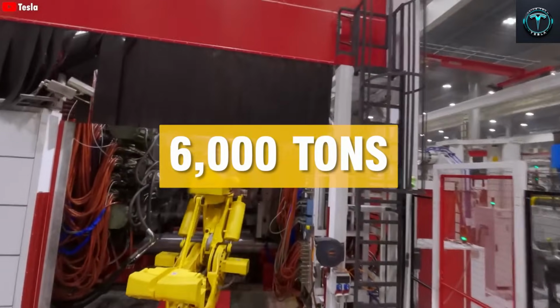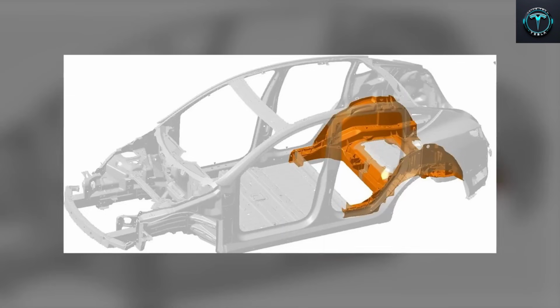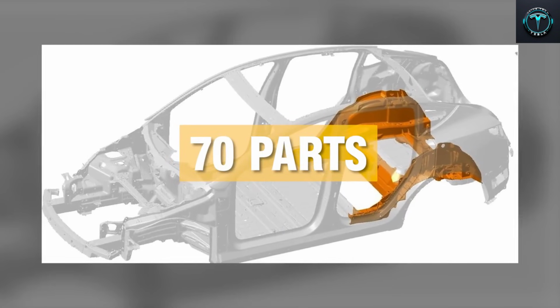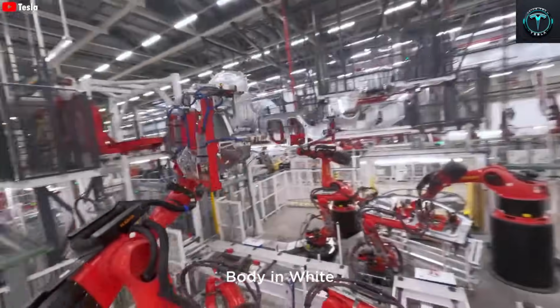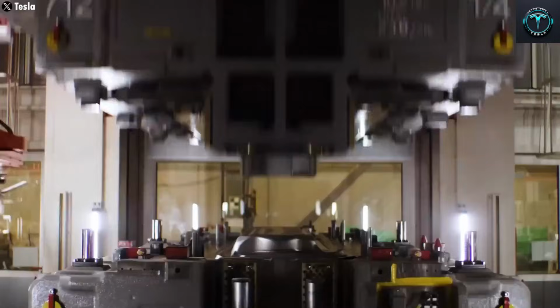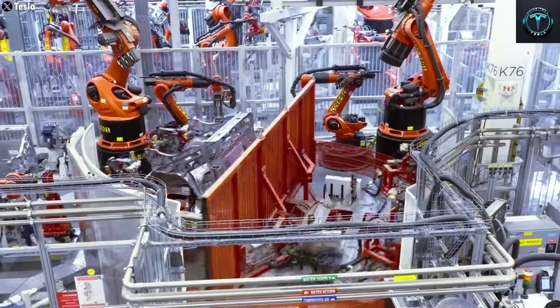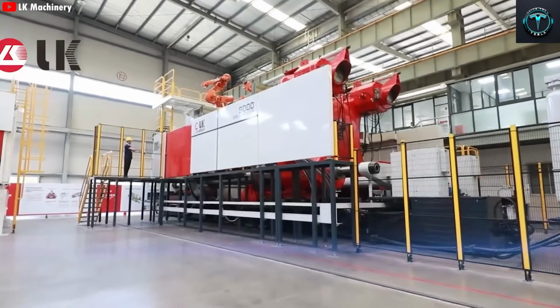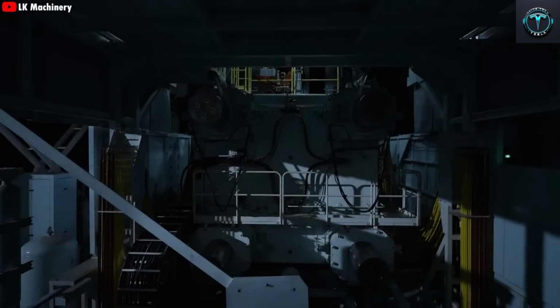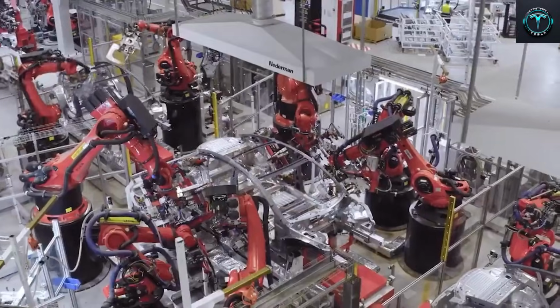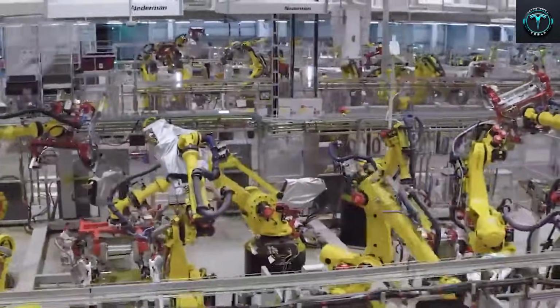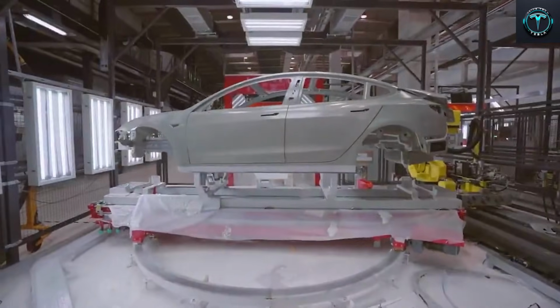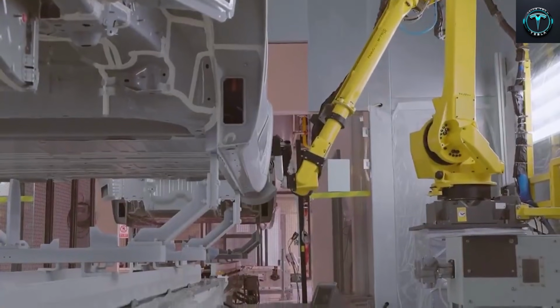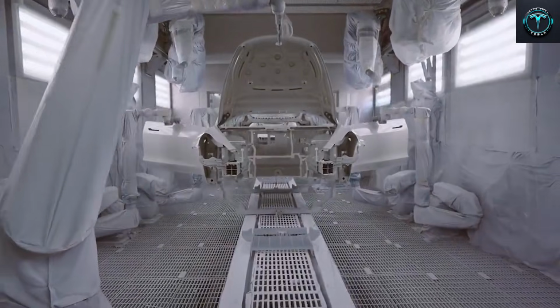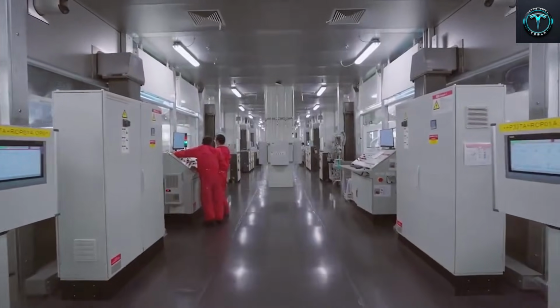Each mold is about 3.5 m wide, 4 m long, and 1.2 m deep, designed to endure the extreme force from high-speed injection pistons that push molten aluminum at up to 10 meters per second. Precise timing and pressure control are vital for the metal to fill every channel without trapping air or cooling prematurely. A built-in vacuum network extracts air before injection, reducing porosity and increasing final structural strength. The casting is finished with an ultra-rapid cooling cycle that drops the frame's temperature from around 400°C to about 50°C in mere seconds. AI-enhanced X-ray, thermal, and pressure sensors continuously evaluate quality throughout the cycle, giving Tesla a fast, highly efficient, and consistent manufacturing platform essential for the Model 2's high-scale production.